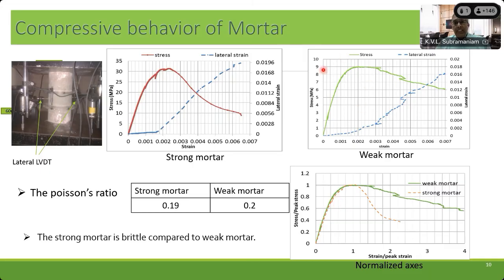Now, if I actually normalize the stress strain curves of the strong and the weak mortar, what we find is something that looks like this. The weaker mortar has a very gradual decrease in the stress after the peak load, whereas for the stronger mortar, the decrease is very, very rapid. So it's basically, again, something very typical of concrete-like materials, where if you make them stronger, the material becomes more brittle. That's what you're seeing here. So when we went to the stronger mortar, the material does become more brittle.